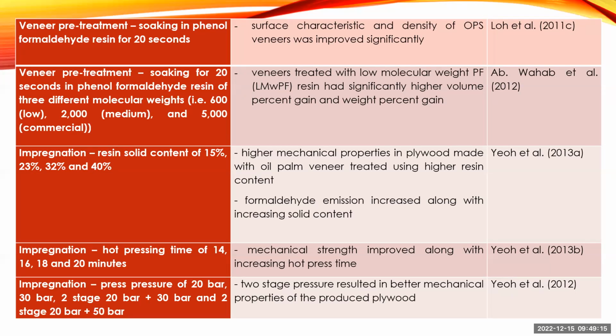Impregnation was tested using different resin solid contents of 15, 23, 32, and 40 percent. We found higher mechanical properties in plywood made with oil palm veneer treated using higher resin solid content.